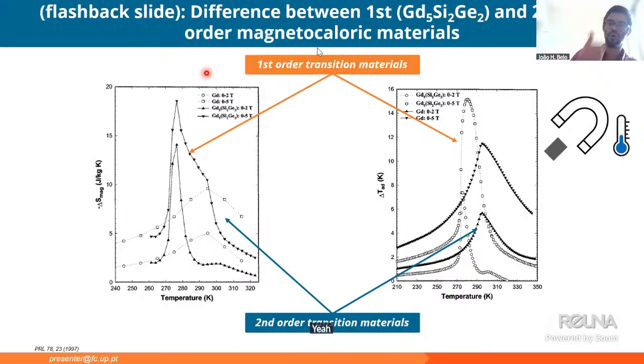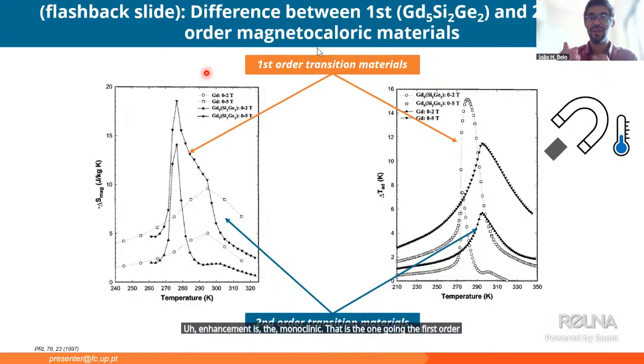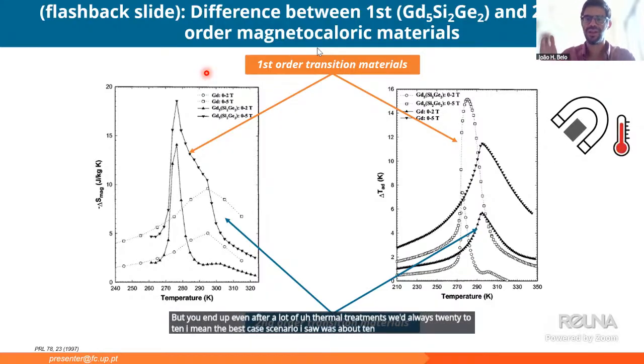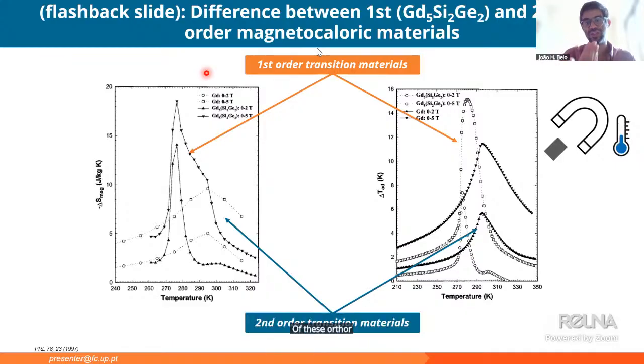That is the one undergoing the first order phase transition. But even after a lot of thermal treatments, you always end up with 10 to 20 percent of the other phase. The best case scenario I saw was about 10 percent of this orthorhombic, which is a different structure and has a different, higher TC, at about 300. So indeed, what you nicely saw can be deconvoluted into two peaks, where the high temperature peak is the magnetocaloric effect of that phase.